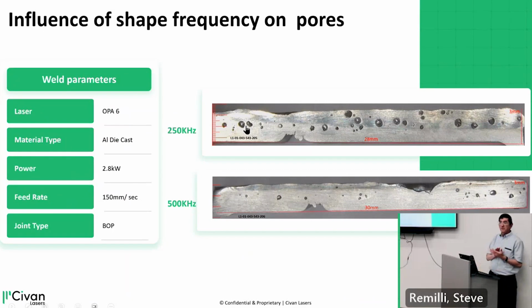Another interesting example is when you weld die-cast aluminum. When you do mass production, die casting is the most popular and cheapest way to do a complex part in mass production. The problem is that when you pour the aluminum at high pressure into the mold, it absorbs a lot of gas. And that's okay, it doesn't affect the properties of the metal, but when you try to weld it, all the absorbed gas boils, pops out, and creates spatter and porosity. So people in practice don't really weld die-cast material, they use other joining technologies. But with our laser, you can actually weld die-cast material because of controlling what's happening in the melt pool.